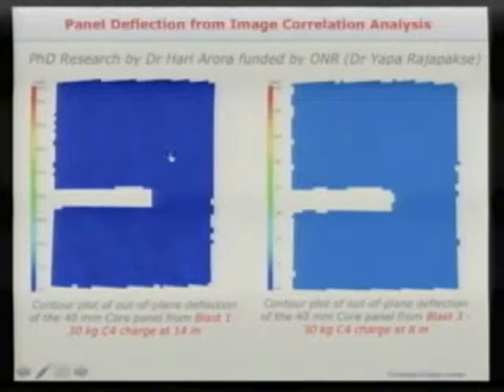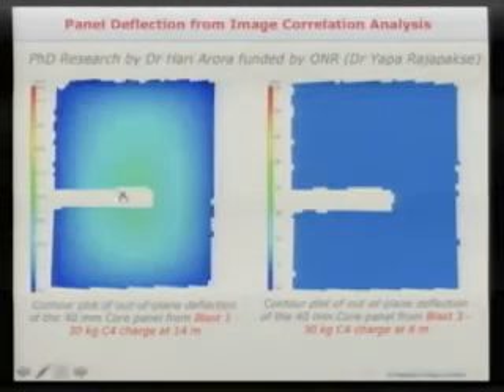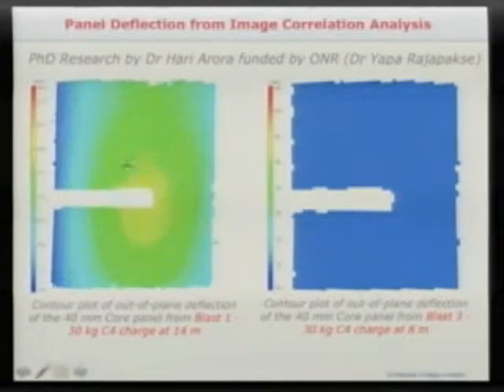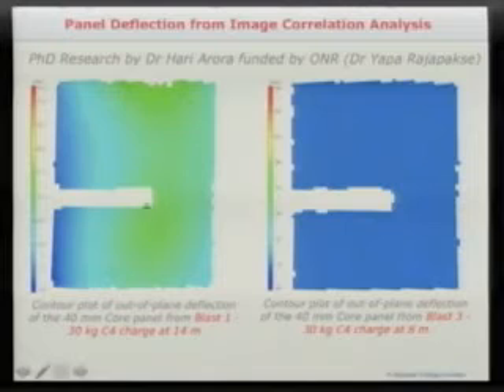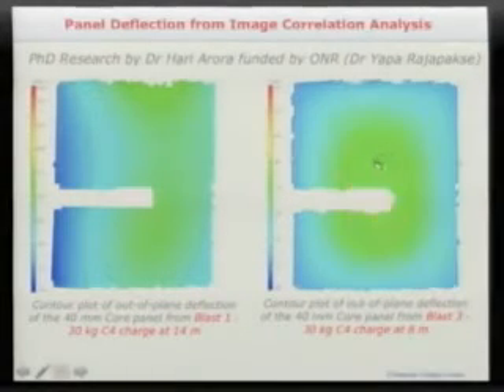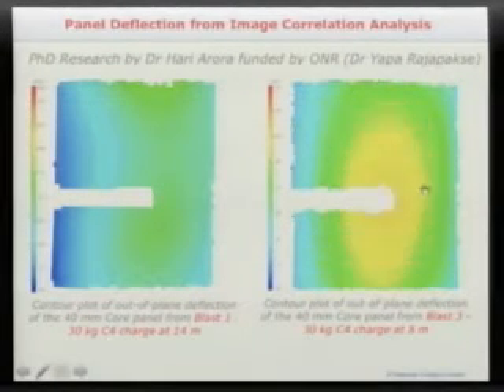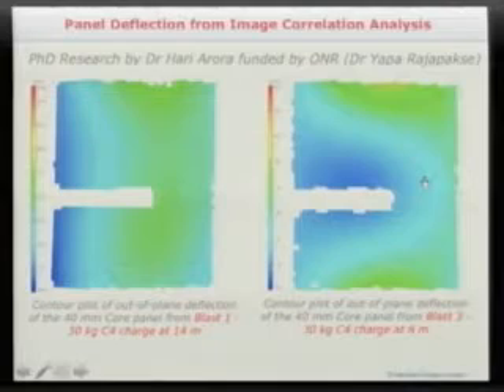And then we capture the data, we run our strain visualization software on it, and this shows we lose the data in this region because of the laser gauge, but you can see it's fairly symmetric, and this is displacement here, out-of-plane deflection, is fairly symmetric. And this one, the blast is closer in at 8 meters, and you start to see a little bit of asymmetry here with a bit more deflection on the right.